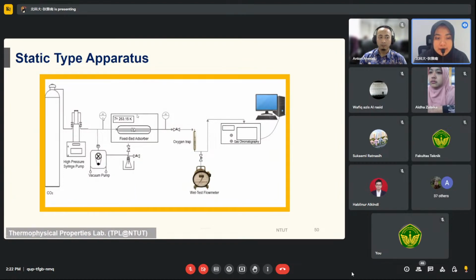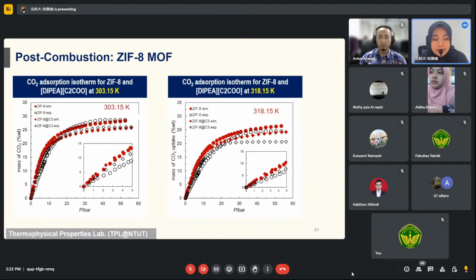So we go from low pressure up to high pressure, and the curve will be like this. We have the open circle and the open diamond here. The open circles belong to the ZIF-8, and the open diamond belongs to the ZIF-8 encapsulated with the ionic liquids. If you see here, at low pressure the composite is better than the pristine one, with no ionic liquid. This is the mass of CO2, and it is much higher. For example, at the same pressure, the open diamond gets more CO2 compared to the pristine one. So the composite is better for pressure from 0 up to around 20 bar.